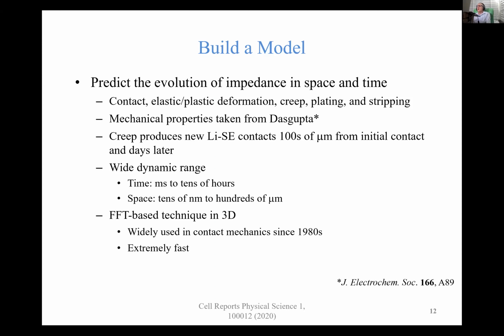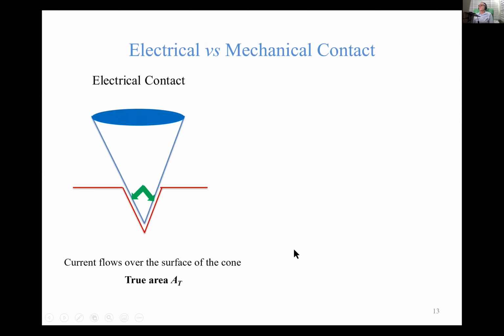What this means is that our model is going to have to cover a very wide dynamic range, running from milliseconds to tens of hours and from tens of nanometers to hundreds of microns. To do this in 3D and in time, with a spatial resolution required on the order of a micron, would be extremely difficult if you wanted to use finite element. And so the contact mechanics field has moved to a fast Fourier transform approach to do this, which is extremely fast, although there are approximations you need to make, of course.